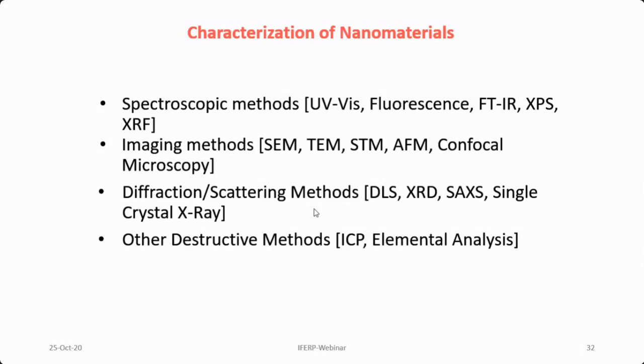Another is SPM based methods. One is scanning tunneling microscopy, which is for conductive substrates. Basically, in our case, metal nanoparticles, alloys, all are conductive. Even their thin films are conductive. So STM is very powerful technique. At the same time, AFM also can be used. AFM normally gives idea about their morphology, their thickness from the substrate, their roughness, surface roughness, all those things can be known by STM and AFM. STM also gives idea about conductivity and all those things from tunneling current measurement and all.